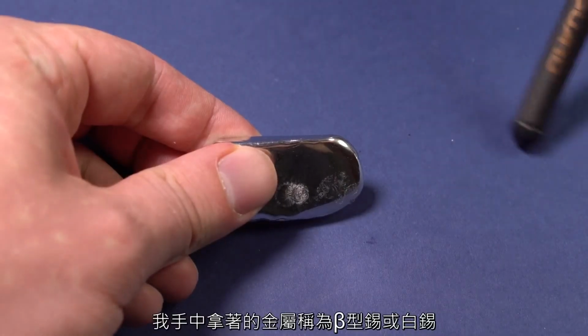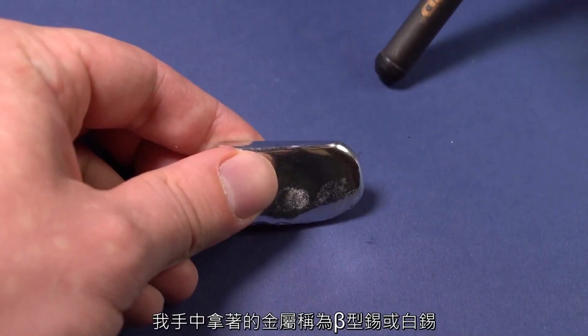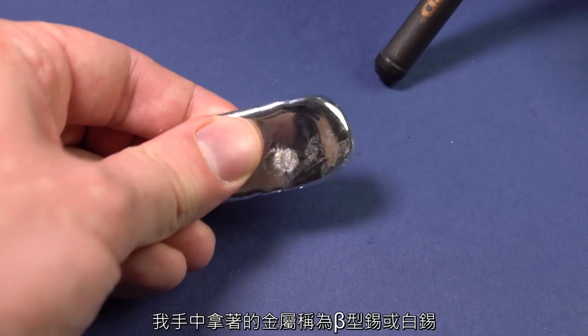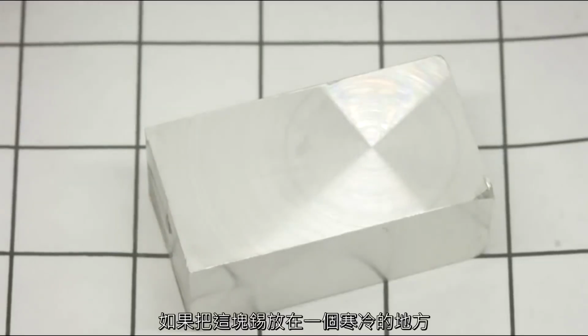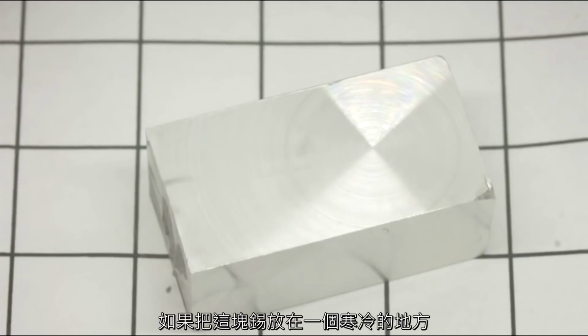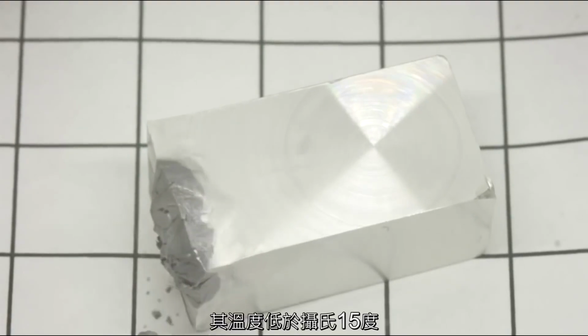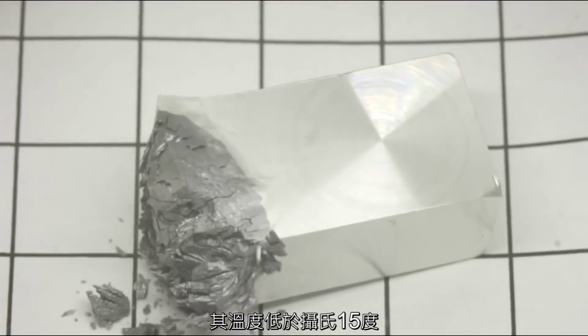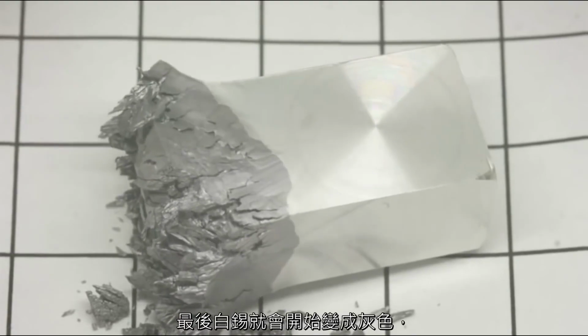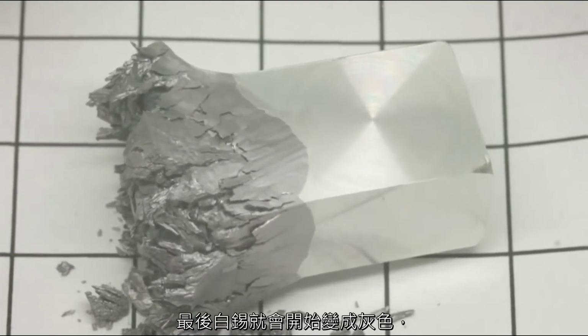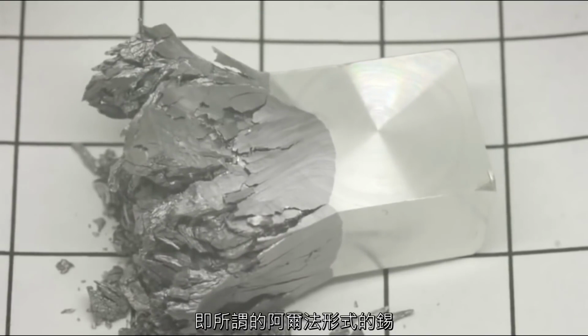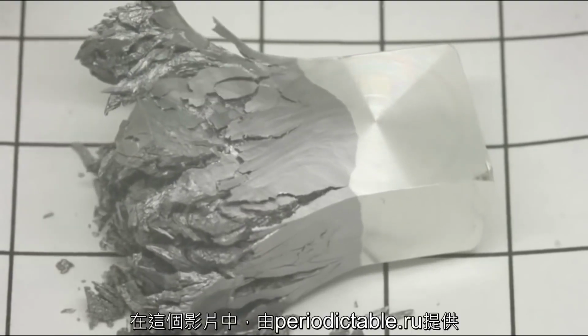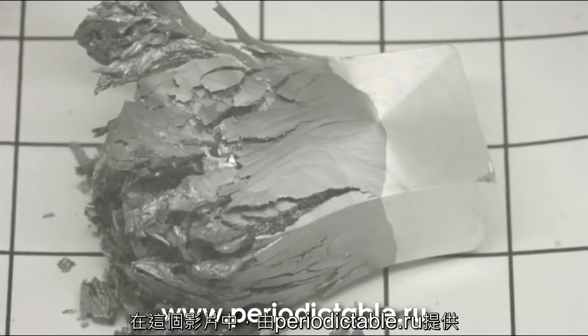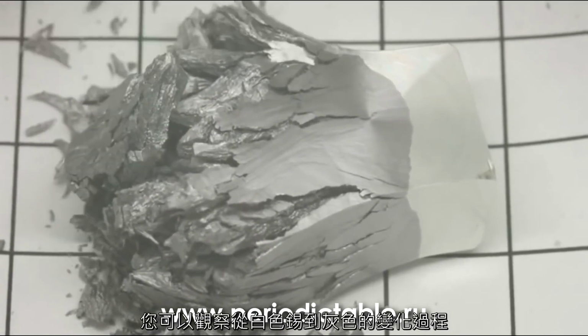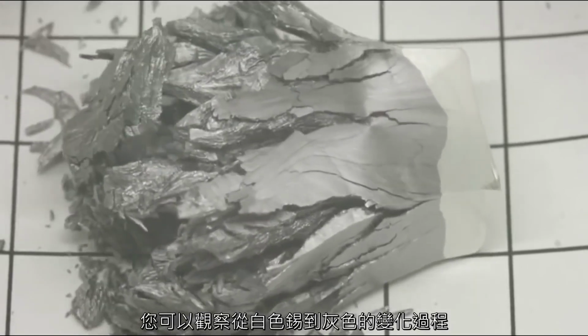The metal that I am holding in my hand is called the beta form of tin, or also white tin. If this piece of tin is put into a cold place, the temperature of which is below 15 degrees Celsius, then eventually the white tin will begin to shift into its gray form, the so-called alpha form of tin. In this video, courtesy of the website periodictable.ru, you can observe the process of the transition from white tin to gray.